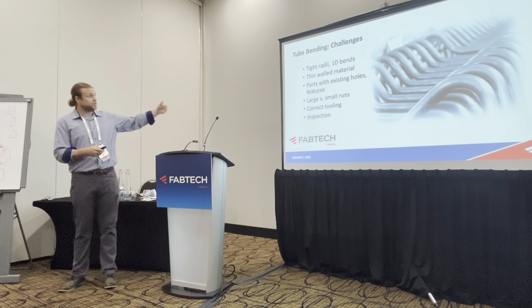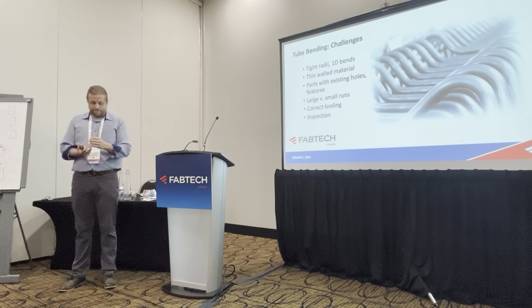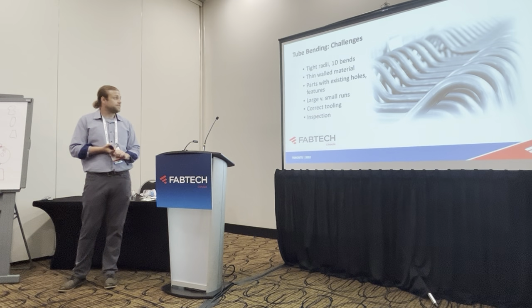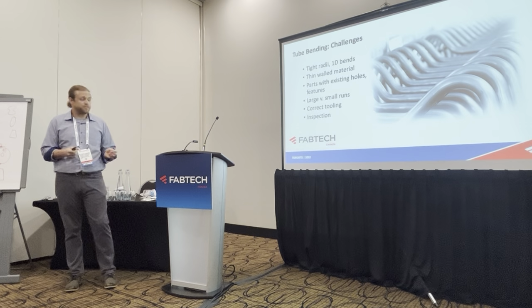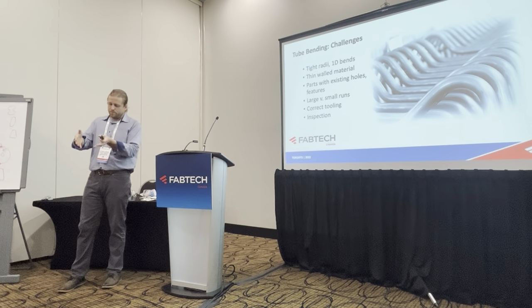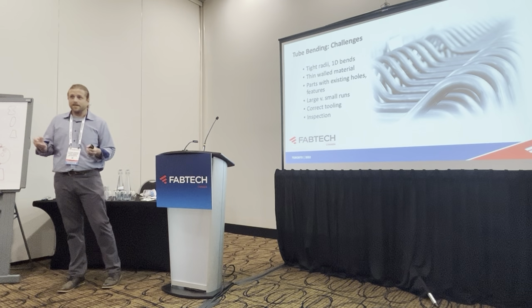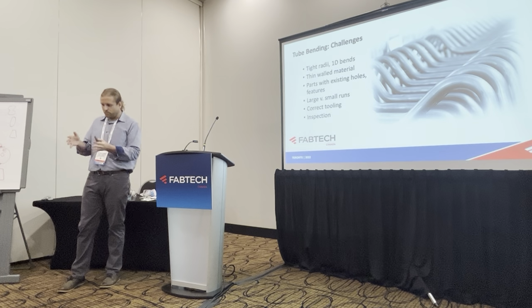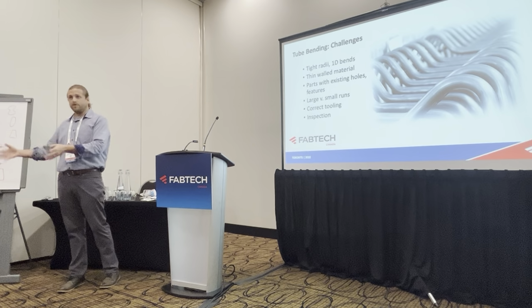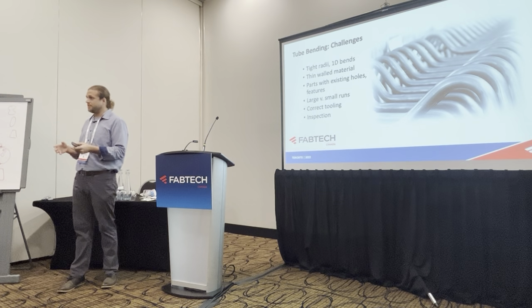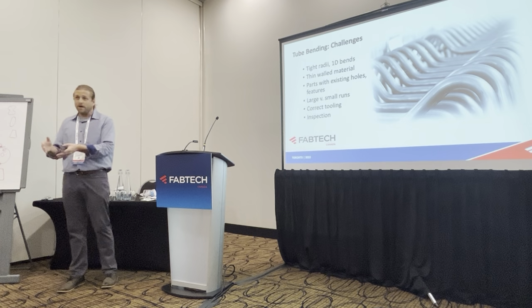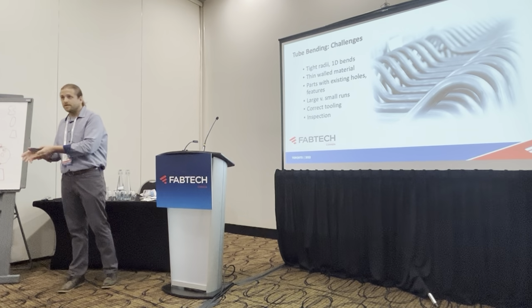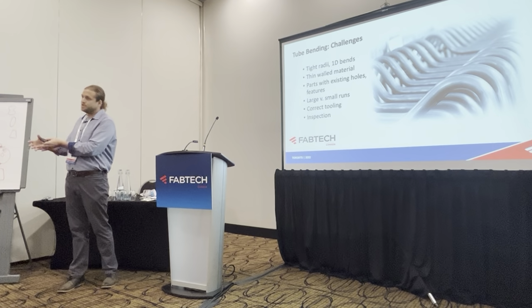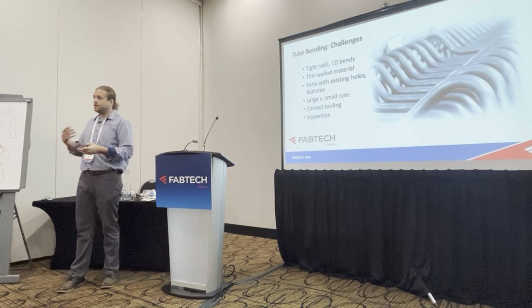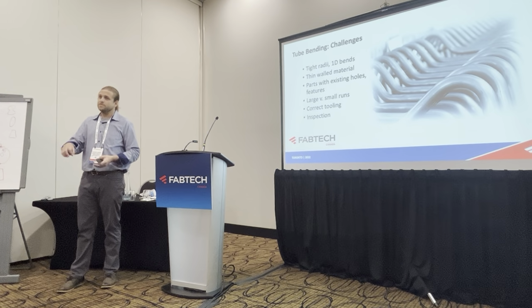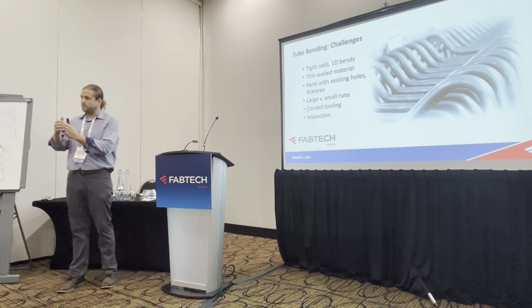We discussed the tooling, the wiper, the mandrel, all of that plays a critical role in executing a successful bend. And then I didn't touch on this, but you can also add to the clamp. When you rotary draw, you always have to have straights between bends, and that can cause issues, because general rule says you need a certain length clamp, certain length pressure die, but you can cheat that. So say a customer has a 3-inch tangent straight between bends, but general rule tells you you need a 6-inch clamp. To alleviate that issue, sometimes you can add knurling or serrations on the clamp to give it extra bite into the tube to eliminate that extra smooth clamp length that would be required to be able to bend that tube.